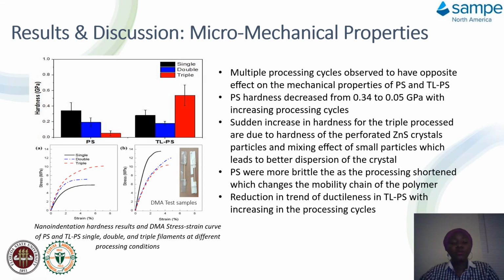So moving on to the micromechanical properties of these 2 materials, polystyrene and triboluminescent with polystyrene, the nano indentation result shows there is a gradual decrease in the hardness of pure polystyrene. At the 3rd extrusion, the hardness of the polystyrene is much lower than at the 1st extrusion, compared to the composite.